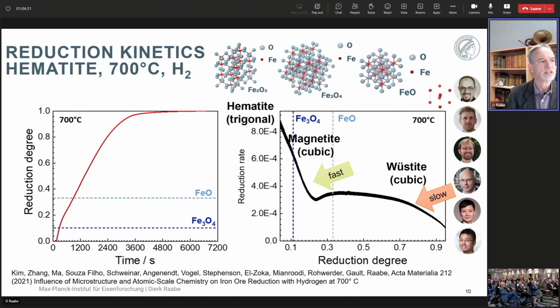This is the reduction kinetics in a static reduction hematite experiment. This is a commercial pellet. I later show you more details about it at 700 degrees centigrade under pure hydrogen exposure. And what you see here, when you look at the right-hand side, where you see the reduction rate as a function of the reduction degree, is the very fast transformation from a trigonal hematite, the Fe2O3, into the cubic inverse spinel. And then the much slower further reduction to the likewise cubic wüstite and to the body-centered cubic iron, because we are at 700 degrees centigrade, which is for an industry example rather cold, but we want to have these reactions not proceeding too fast. So you see you nearly lose an order of magnitude in reduction speed between the beginning and the end.